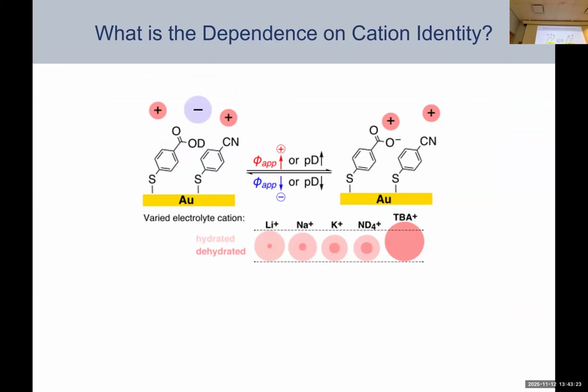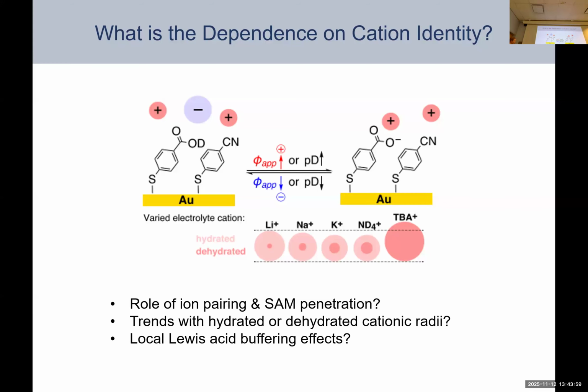Okay, I also wanted to briefly mention some work that we did to understand cation identity. So we followed up, this is a tag on a set of experiments to the same mixed SAM, but now looking at variation in the electrolyte composition. All the previous work I showed you was in potassium phosphate. Here we're looking at lithium, sodium, ammonium, and tetrabutyl ammonium phosphate buffers. Okay. And here's a nice little schematic to show you changes in the hydrated and dehydrated radii of these cations.